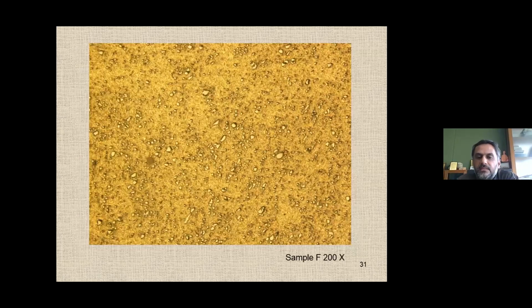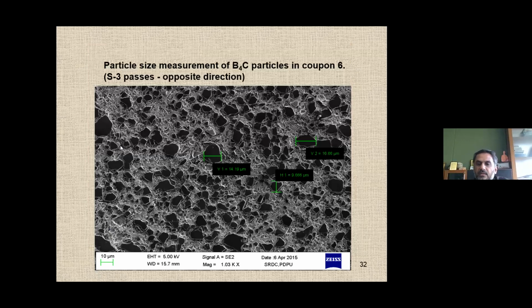And that's the reason you can see here all those white particles. They are nothing but 1 capping plus 3 stirring, but in the opposite direction. That was an optical picture. This is your scanning electron micrograph. You see that these are all boron carbide particles which are distributed uniformly into the matrix of aluminum. And the original size of the powder particles also gets reduced and fragmented during the process. This indicates the uniform distribution.